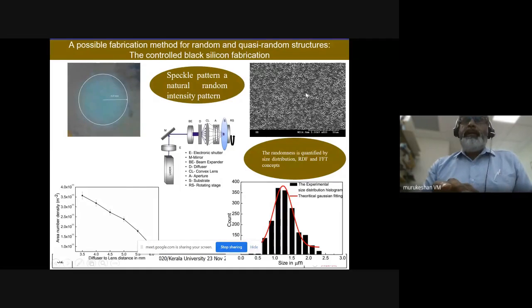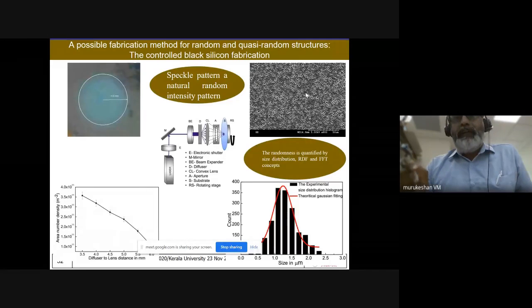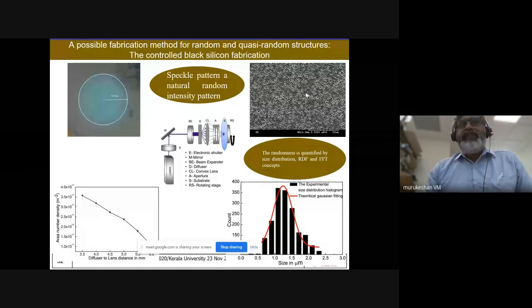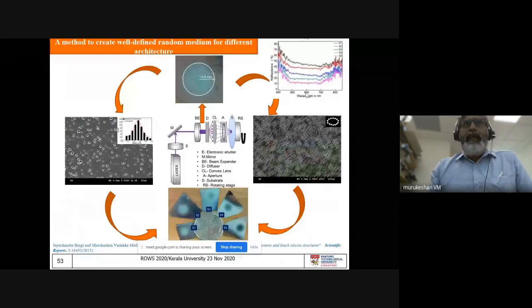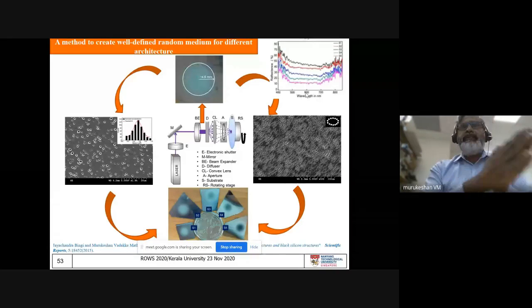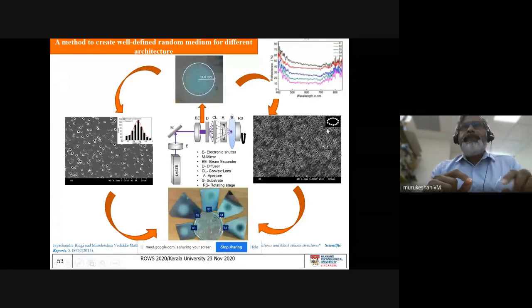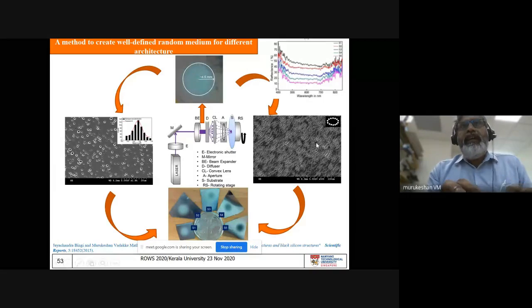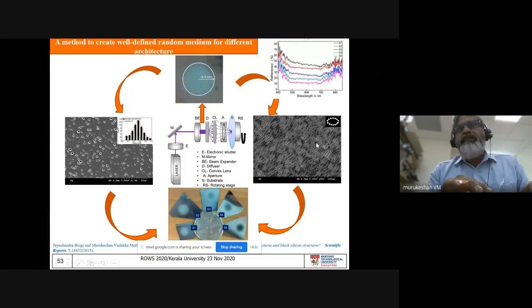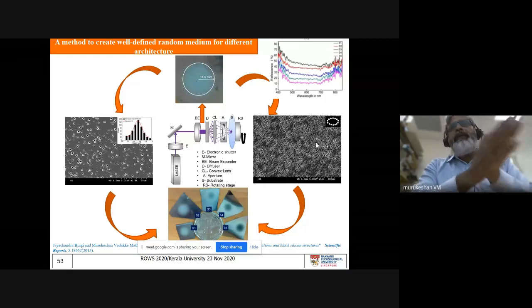But then we need to find some number to quantify this randomness, because it is very important in our work. So we had a few quantifiable numbers such as areal number density, radial distribution, etc. Based on that, we classified a few patterns, and based on this variation of D, CL, and A, as well as the aperture, we are using square aperture, elliptical aperture, etc. We are able to make the density vary by a large amount.